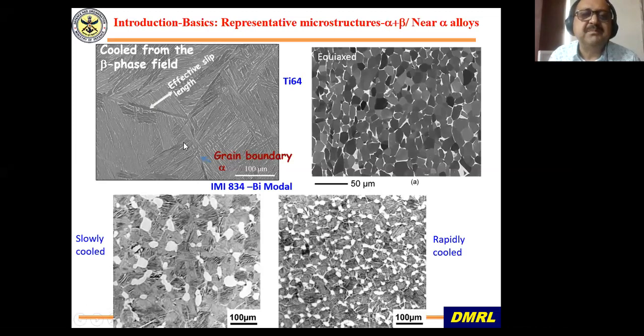If you water quench, you will get martensite. I will show you the martensite, but here it has been air cooled, and you can see different colonies of alpha. This is called alpha colony. That is where the titanium alloy starts becoming complex.